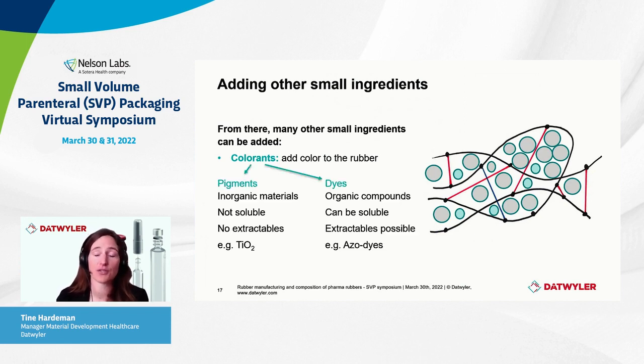Pigments and dyes are the two most important categories, but pigments are really very much preferred in the pharma segment because these are inorganic materials. So this means that they are not soluble and will not give rise to organic extractables, such as, for example, titanium dioxide. On the other hand, you have dyes, but as these are organic compounds, they can be soluble and they can give rise to extractables, which is something that we typically want to avoid.